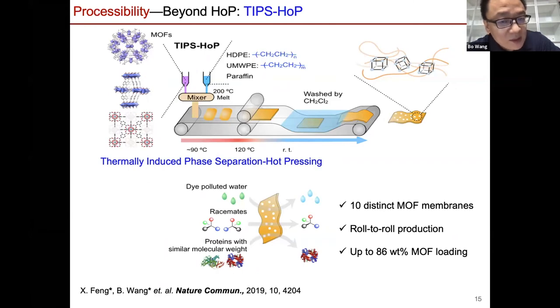We mix high density polyethylene and the paraffin at the same time. Eventually, it will give you a kind of elastic polymer mix. Then through a roller, you just put it into shape and put it into the film. And then we wash out the paraffin using dichloromethane, and it can give you a very nice membrane that way.